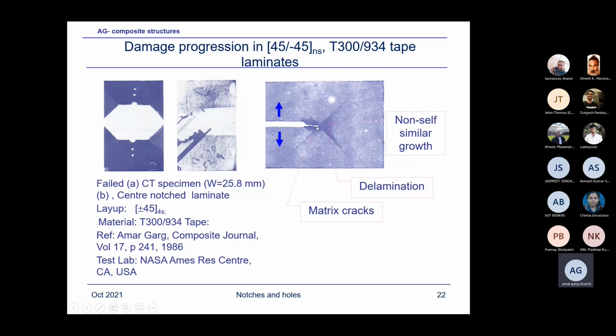So suppose you are testing a laminate with 10 plies, 20 plies, 15 plies, depending upon the layups. Load it and determine the failure load. And then you have the unnotched strength, using the equations which I have shown, those equations calculate. So simply, like 10 ply, 20 ply, 15 ply, depending upon your design layups, you would test various laminates and generate the data sufficient for your design space.